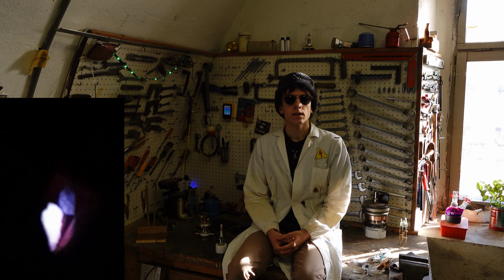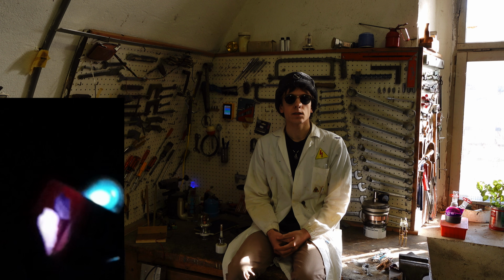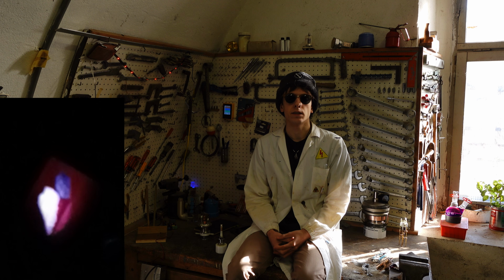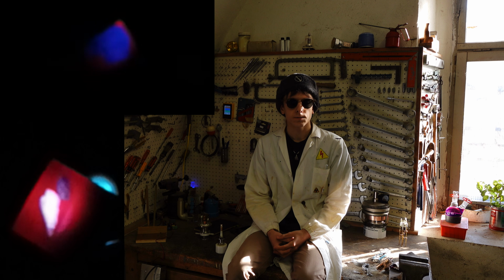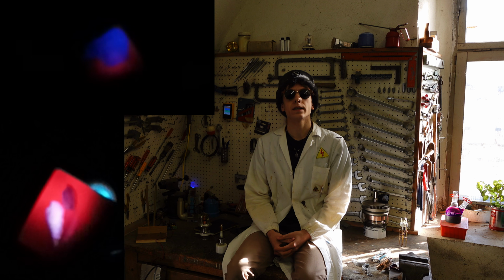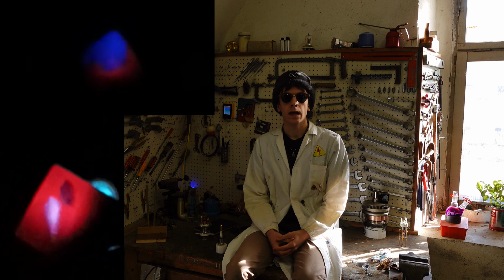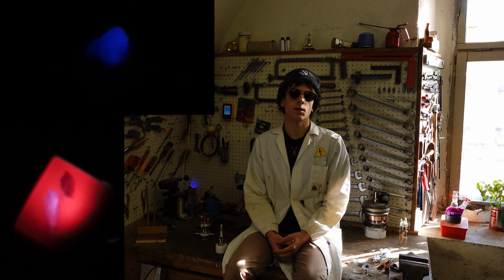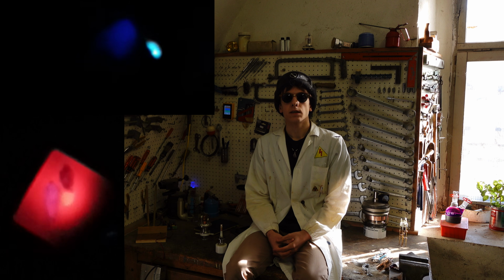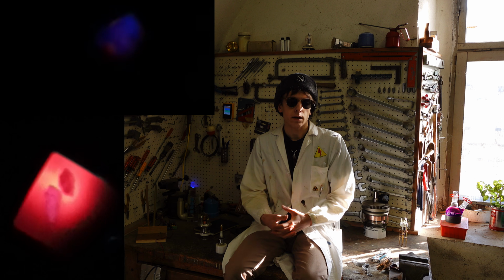We can verify the formation of F-centers by heating the crystal after the irradiation. We should see this beautiful glow of the salt. This phenomenon happens because we are freeing the electrons from their traps, and during this process they decay into a more stable energy, releasing visible light that you can see.